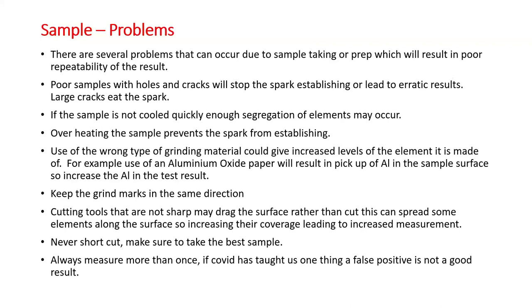In other cases, it just gives you a very poor plasma, and you've got very poor results from there. And obviously, a hole will do the same. You might not be able to see it when you've prepped it, but if there's a hole just underneath the surface, as soon as you start to melt with the creating of the plasma, then it's going to burn through that, and you're going to run into a hole. If the sample's not cooled quickly enough, you may get segregation.